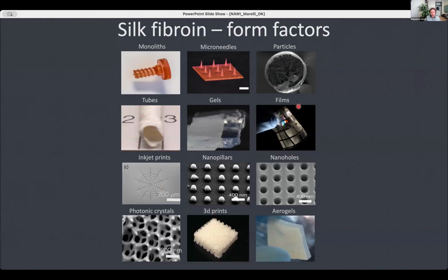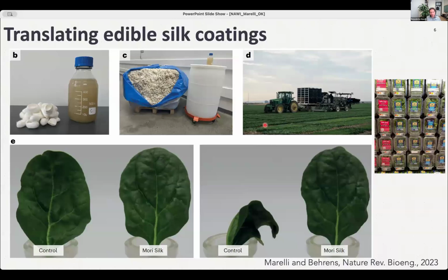So all the material formats that you see here are done with molecules of silk that have been self-assembled to impart a new form factor. The same principles can be applied to other materials that we can extract, both proteins and polysaccharides. So we're thinking about, for example, cellulose, we think about chitosan, we think about, in some cases, keratin or alginate. In the case of silk, my lab has shown that it can be scaled up to have impact. So this is just to give an idea that these materials are real and can be scaled at the right cost to have impact on large commodities.